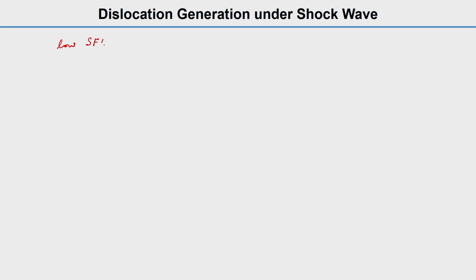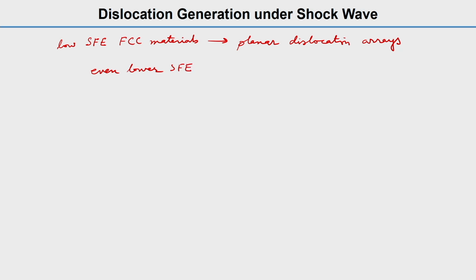Similarly, for low SFE, that means low stacking fault energy FCC material, planar dislocation arrays are generated, and even if it is lower stacking fault energy, so stacking fault, SF, and twin fault, this is another fault, so twin faults are prominent. Okay. So, then we will not talk about BCC or hexagonal close pack, or let us say intermetallic compounds